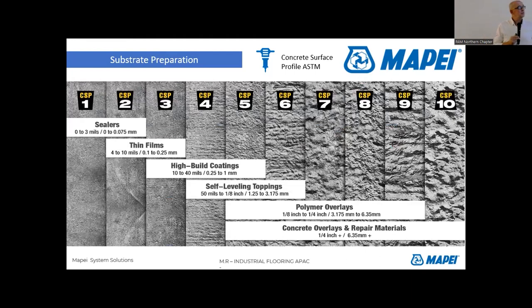So here we follow the CSP 1 to 10. And if you say I have a coating of 1 millimeter, but my surface looks like 7, I have a problem, right? So coming back to my other slide again, if I have 1 millimeter, I'm usually using 2 or 3 or 4. 4 is already on the edge. But if I have a roller coat, which we're talking about in microns, I can use CSP 1, CSP 2. Sometimes the client doesn't mind and says, I see a little bit of the ground and the profile, but it's okay. So here are different samples which you can have a look at, which show the different CSP values. And then on site you say, we made an optical inspection. There could be a specification for optical inspection of the surface before application of the primer. That could be one condition in the specifications.